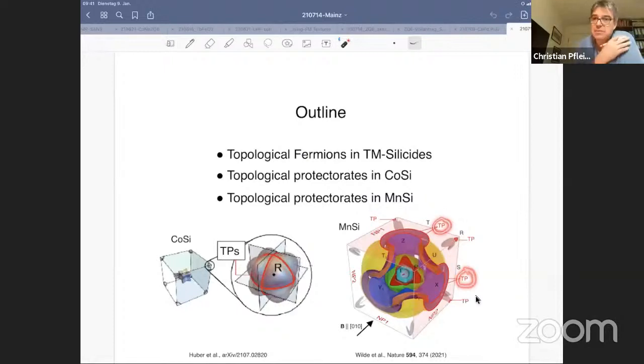And now the nice thing we can do here is we can, of course, change the orientation of the field. And when we change the orientation of the field, we can switch on and off these topological protectorates of different parts of the Fermi surface. And this, we expect, will have consequences for the transport properties. What I will show now is just the studies of the Fermi surfaces. We're not so far that we can make a full conclusion for the transport properties, but I think this is a very important conceptual step.